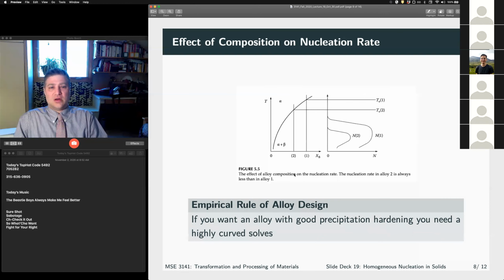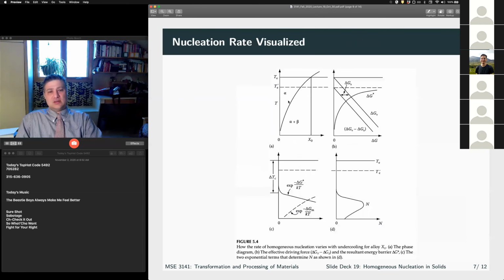Okay, and so that's where we're going to stop, right? This is really the only new concept that we want to talk about in terms of diffusional solid state phase transformations, right? Well, actually two, right? We have the strain energy component and the fact that the rate also depends on our ability to diffuse, right? And you can also guess that phase transformations such as massive that don't require long-range diffusion have much higher nucleation rates than those like precipitation and eutectic transformations that do require long-range diffusion. Okay, so we'll stop there. We'll see everyone Wednesday.